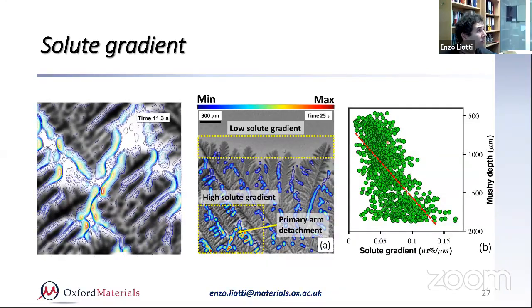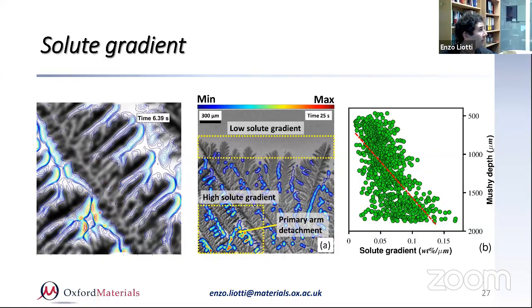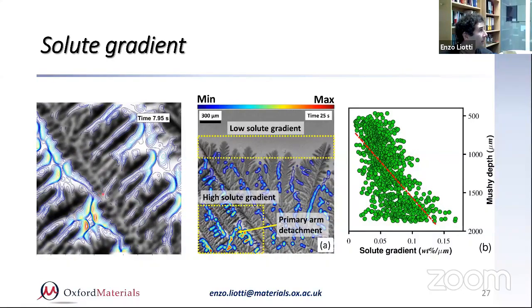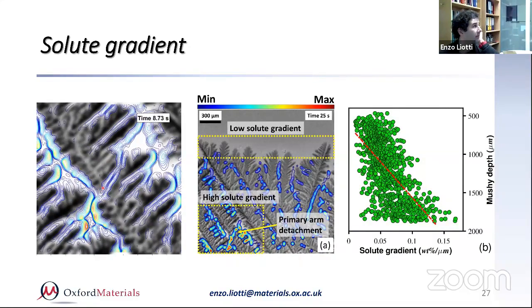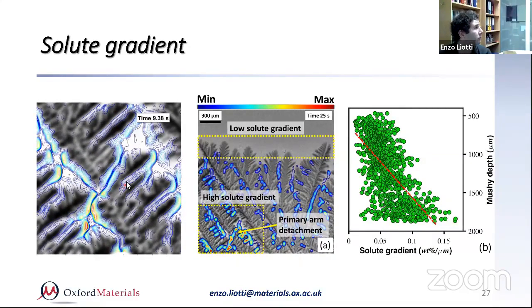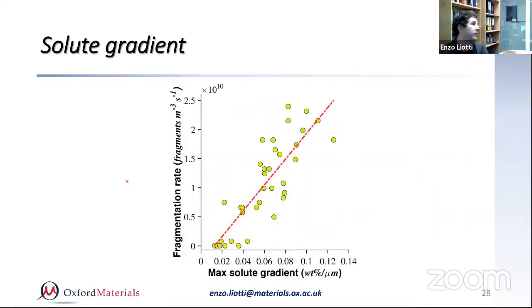These are individual measurements of the solute gradient in the horizontal direction as a function of the depth in the mushy zone. And here shows a fragmentation of a primary dendrite, and you can see that the gradient was very high in the local area nearby the breaking. So what this is telling us, well, when we started to compare the fragmentation rate with the solute gradient, we found a correlation. So essentially, this is important to understand the mechanism. The higher the solute gradient within the liquid, the higher the fragmentation rate.